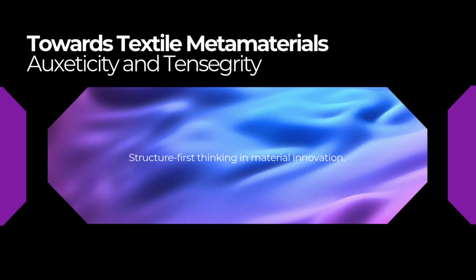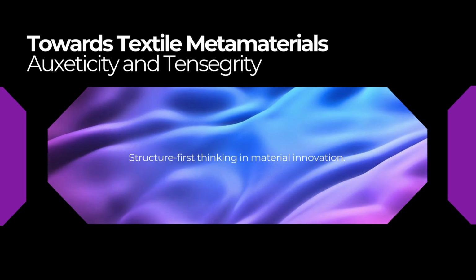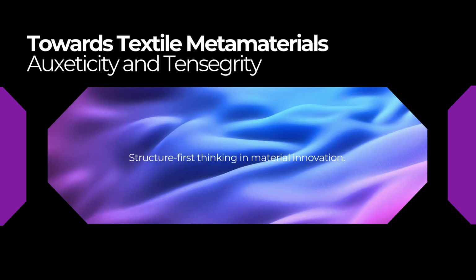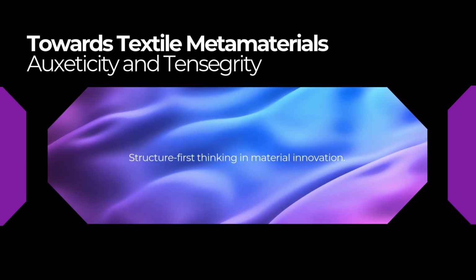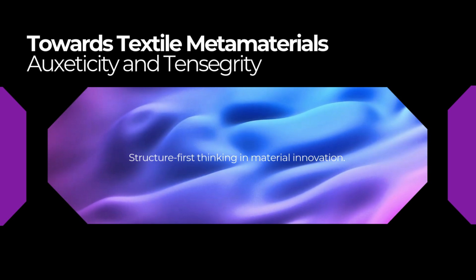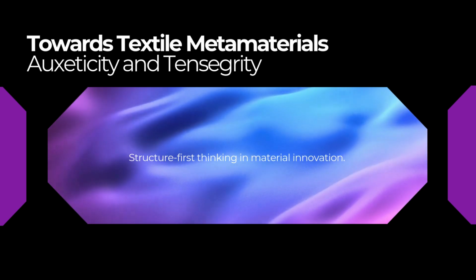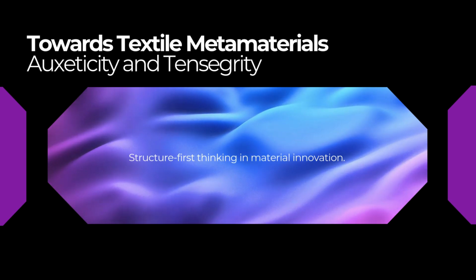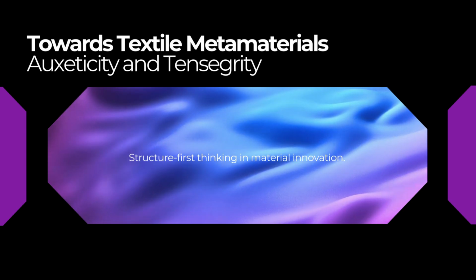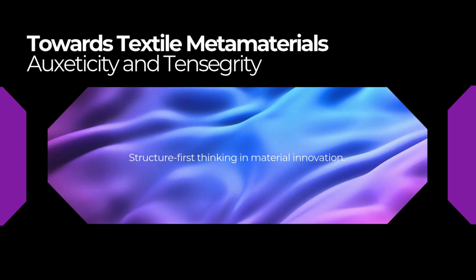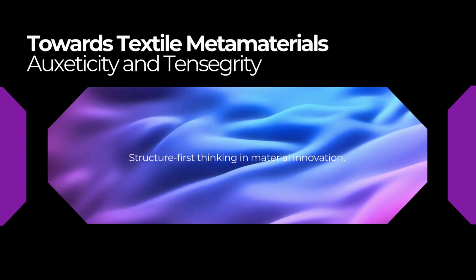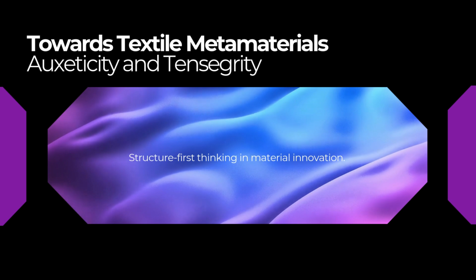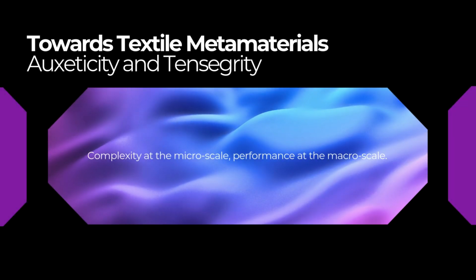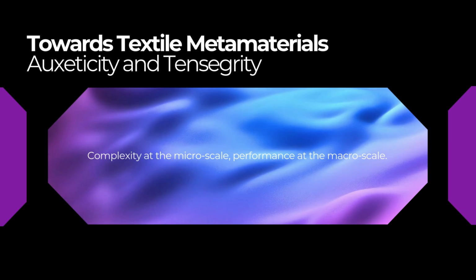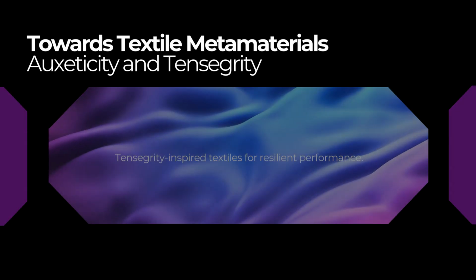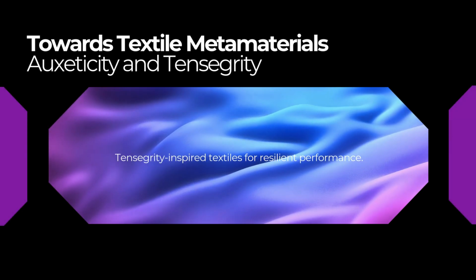We've seen these really compelling similarities between the stiff felt and theoretical tensegrity models. You have the bent columns as compression struts and the bonds as tension cables. So the final provocative thought for you, the listener, to mull over is this. We saw the trade-off. The strength increased, but at high strain, the recovery failed. So what specific performance parameter, something you can measure during that thermal treatment process, could define the precise point when a textile successfully integrates both enhanced auxeticity and the resilience of tensegrity without sacrificing its future reversibility? Think about that crucial balance point.